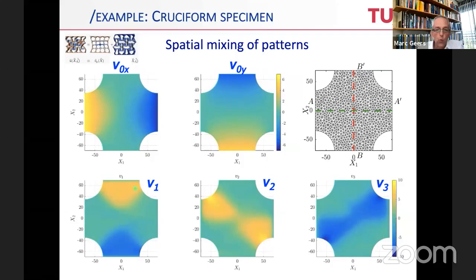And we see where this magnitude develops spatially in the cruciform specimen. In order to interpret this in pattern, you will have to make the linear combination of the different modes to identify which pattern is actually visible there. But it shows that you can really deal with spatial mixing of patterns in a finite structure and the time evolution of those patterns. And this is actually what the whole micromorphic scheme was precisely after, with a continuum that is very efficient in doing so. That's actually the key result of this analysis.